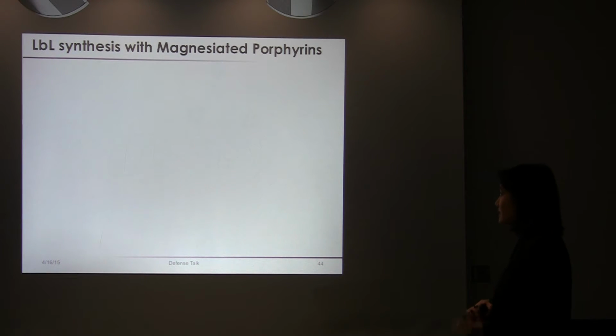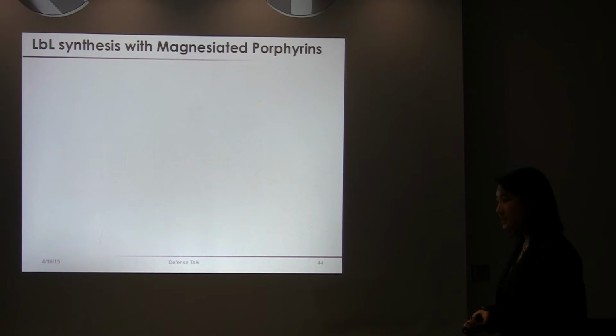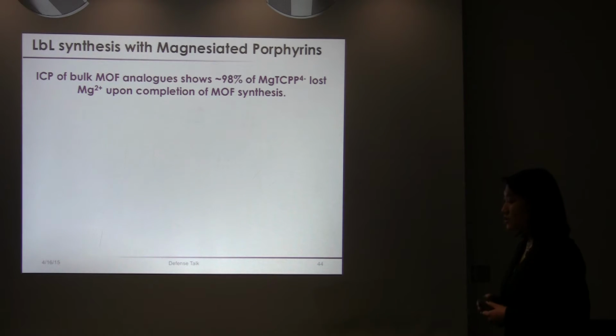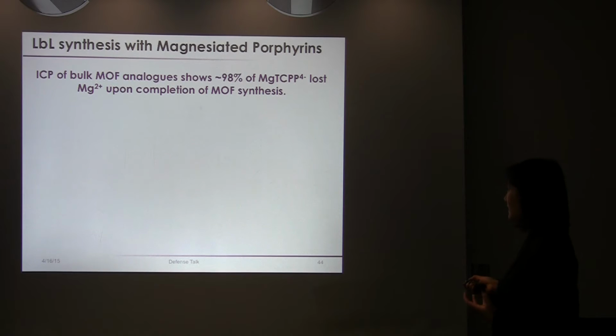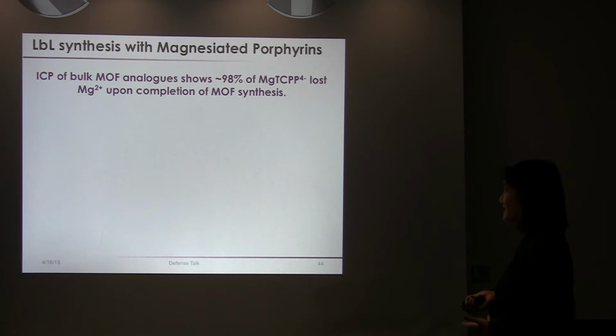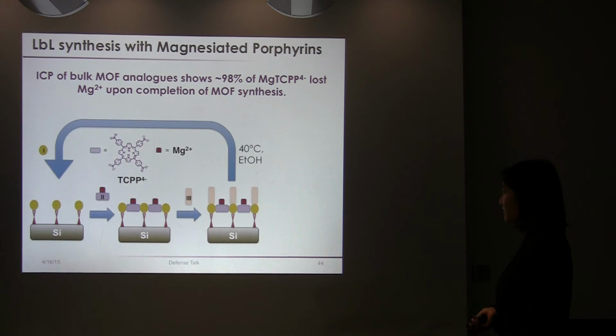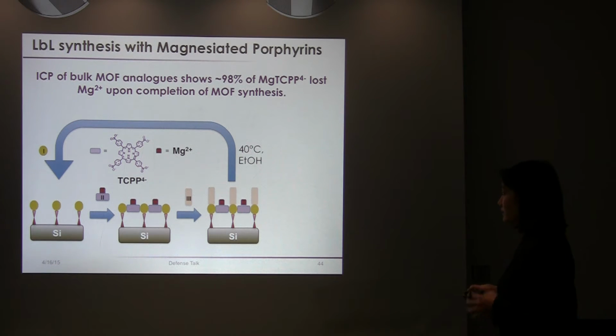And also, since I was inspired by the success of this post-synthesis magnesiation reaction, I also wondered if the synthetic conditions would affect the actual magnesiation of the porphyrins in the MOFs. So previously, we had seen that in just normal bulk MOF crystals, there was only a retention of about 2% of the magnesium in previously magnesiated tetracarboxyphenylporphyrin by ICP. So I wondered if we could retain all of the magnesiated porphyrins by using layer by layer synthesis, because essentially using solvothermal synthesis, there's the acidic residue as well as the high temperature would spontaneously metallate the porphyrin linkers. But using this layer by layer assembly, there's very adequate rinsing after each step to remove any acidic residue that might be formed from the acetic acids from the zinc acetate metal precursors that are used.